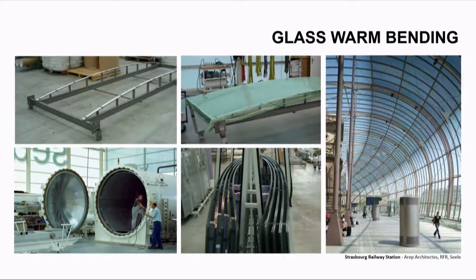People also call it laminate bending, which consists in stacking glass and interlayers, putting them into a vacuum bag, clamping into a jig, and putting that jig into an autoclave and laminating those things together. And what's happening then is when you take it out, the bond between the interlayer and the glass, the shear at this interface, prevents the glass from coming back flat again. So it still has this spring back. It wants to become flat again, but the presence of the interlayer keeps that together.